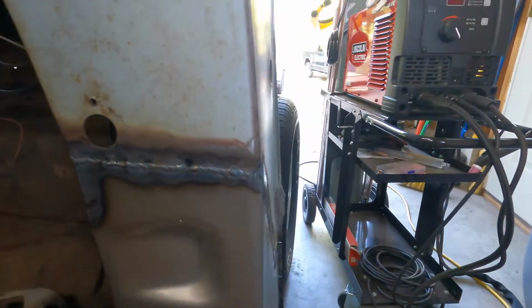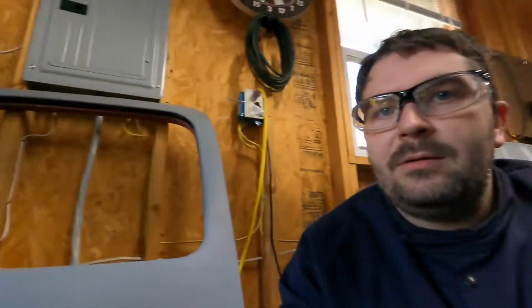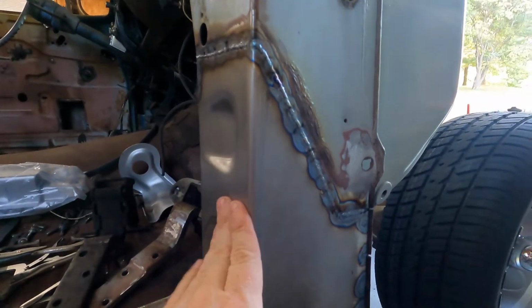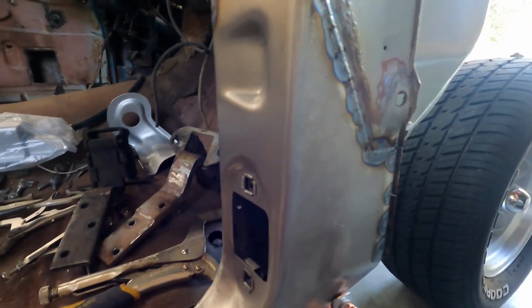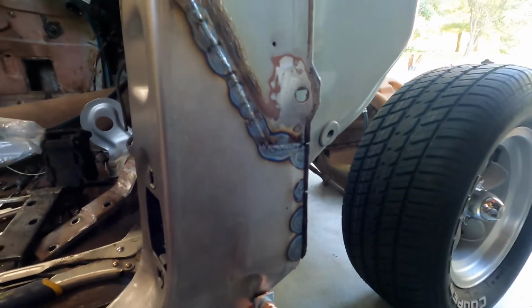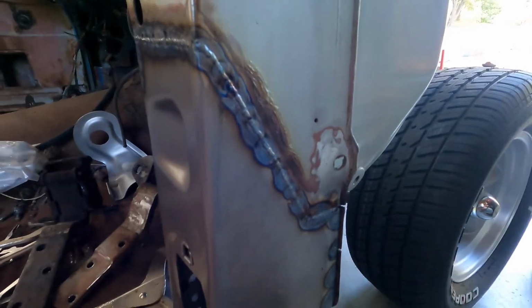And the heat control, you can see I welded around that hole for that door jamb switch for the dome light, and it didn't blow it out. The panels on this A-pillar are particularly sturdy. They're pretty thick, so they were able to take heat a lot better than a fender or something. Like this C10 door that I've got behind me, that's a lot thinner metal than the 55 Chevy is. This is from an 85 C10, so it's a little more forgiving on these older cars with thicker metal.